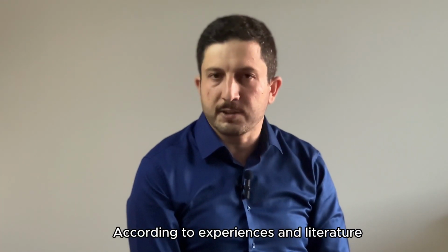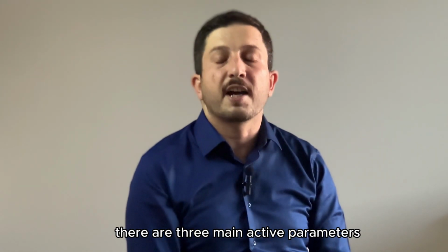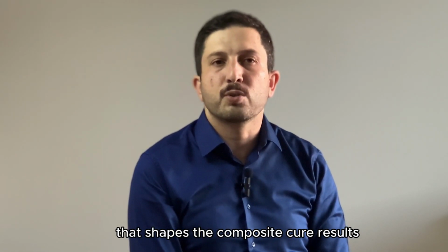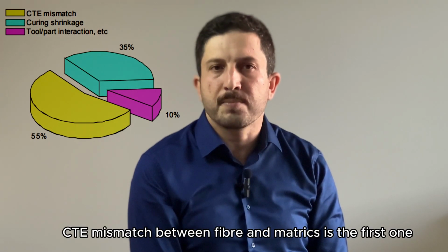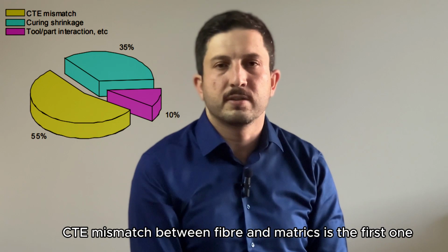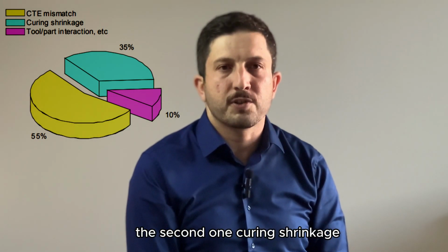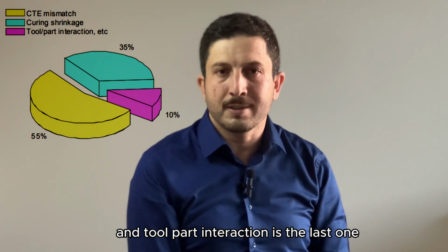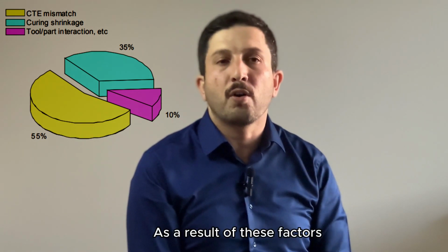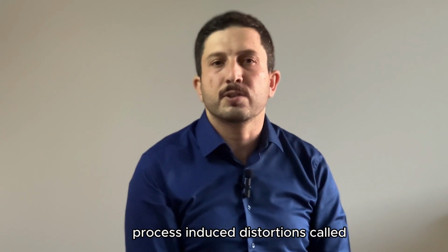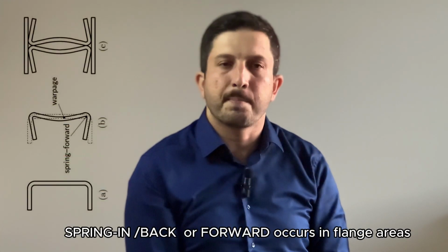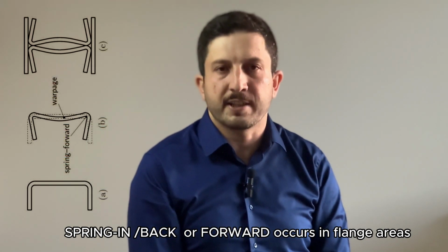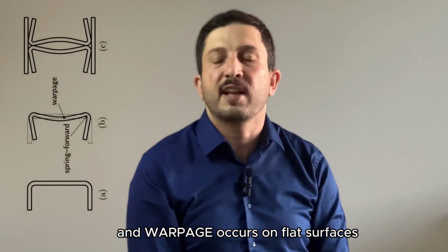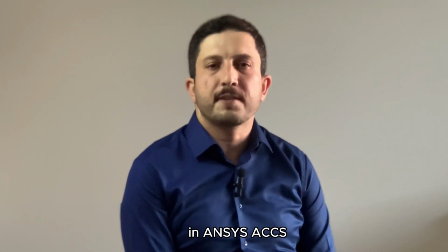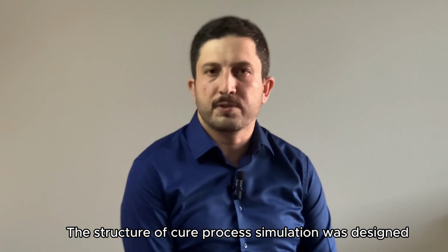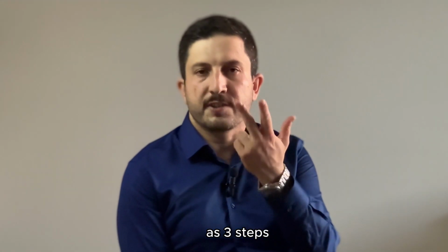According to experience and literature, there are three main active parameters that shape the cure results. CTE mismatch between fiber and matrix is the first one. The second one is curing shrinkage. And tool-part interaction is the last one. As a result of these factors, process-induced distortions called spring-in, and spring-back or forward, occur in flange areas, and warpage occurs on flat surfaces. In ANSYS ACCS, the structure of the cure process simulation was designed as three steps.